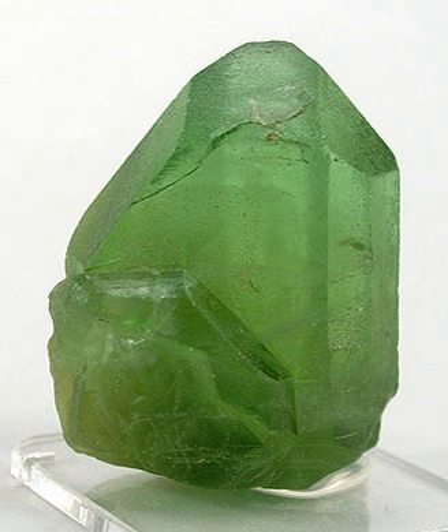Experiments have documented that olivine at high pressures, e.g., 12 gigapascals, the pressure at depths of about 360 kilometers (220 miles), can contain at least as much as about 8,900 parts per million weight of water, and that such water content drastically reduces the resistance of olivine to solid flow. Moreover, because olivine is so abundant, more water may be dissolved in olivine of the mantle than is contained in Earth's oceans.